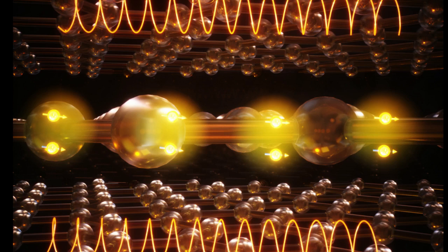As they increased the magnetic field around tri-layer graphene, they observed that superconductivity held strong up to a point before disappearing, but then curiously reappeared at higher field strengths.